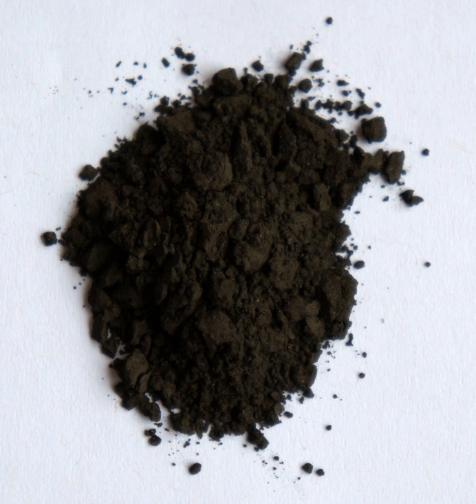Hydride formation has been linked to the presence of hydrogen in the surface of a Ti alloy. Hydride particles are observed in specimens of Ti alloys that have been welded, and because of this, welding is often carried out under an inert gas shield to reduce the possibility of hydride formation. Ti alloys form a surface oxide layer, composed of a mixture of TiO2, Ti2O3, and TiO oxides, which offers a degree of protection to hydrogen entering the bulk.